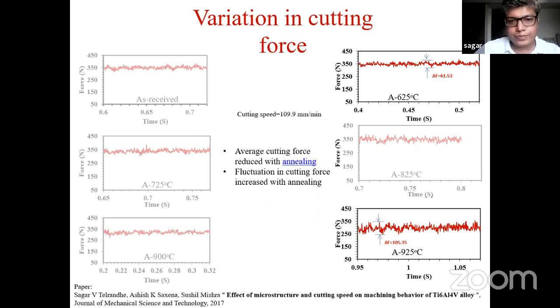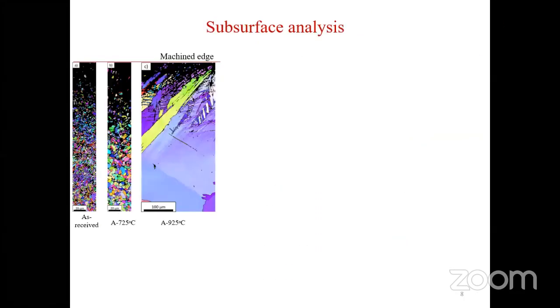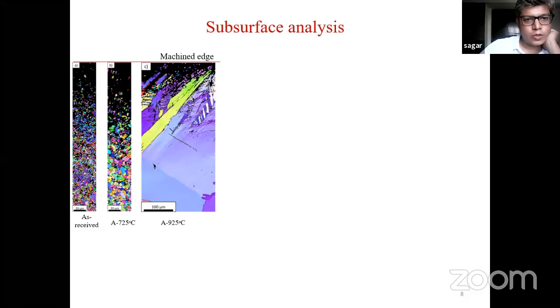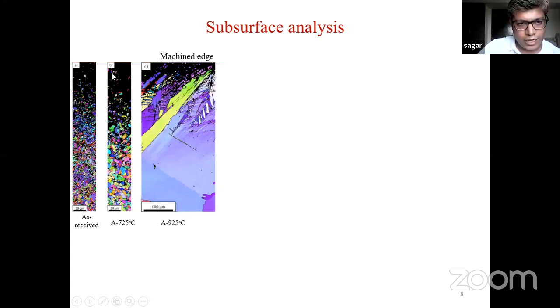So moving ahead, we did the subsurface analysis after machining also. Here you could see, after machining there is a finished surface forming up. If you cut the cross section of that finished surface and see in the thickness direction how the machining process has disturbed the basic structure. Because of machining, a local deformation has formed. That's why in EBSD we could not index these regions. These are the black regions. But here we could still see what different kinds of things have formed due to machining at the subsurface.